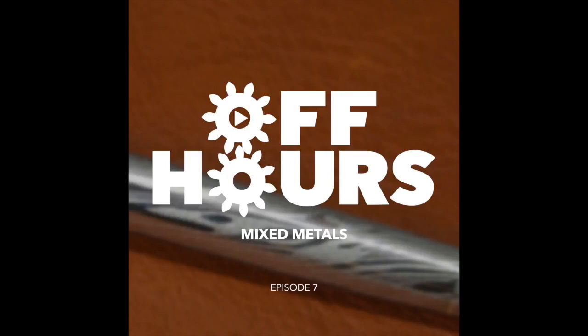And you would think, okay, two white metals together, that doesn't make a lot of sense. But there's enough of a difference between the two and how white they are, and you actually get a considerable difference in terms of how they look. So you can see that grain structure come out. It's quite nice. Tantalum would be an interesting metal to mix in, but not particularly cheap to work with. See, they get that bluish gray sort of white metal.